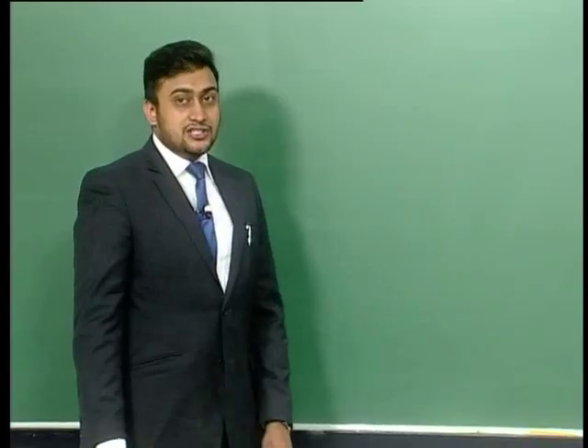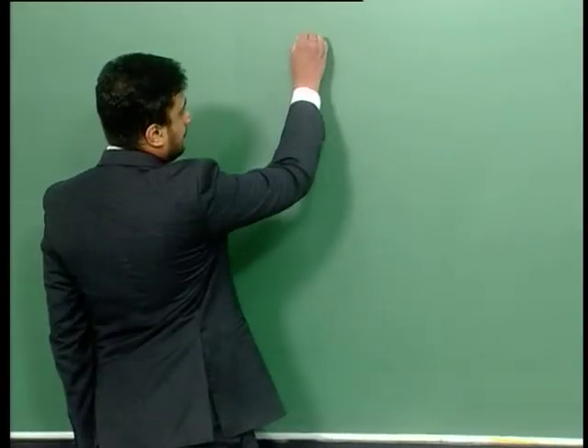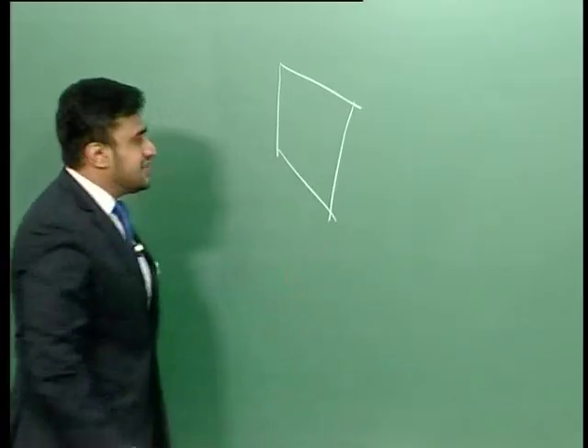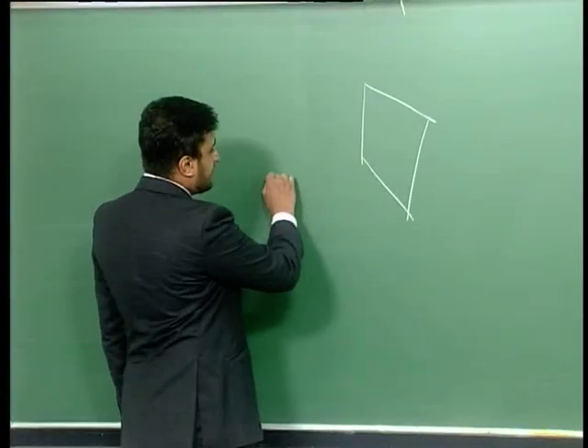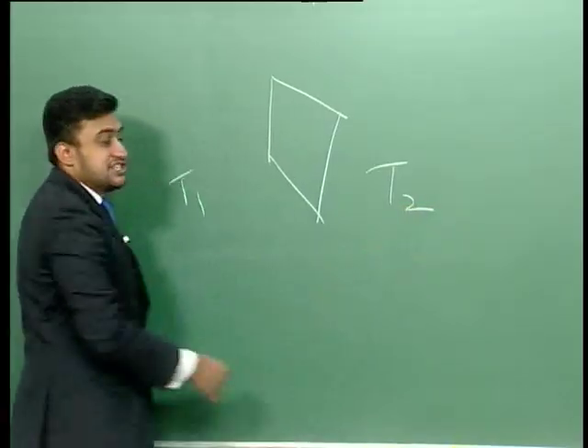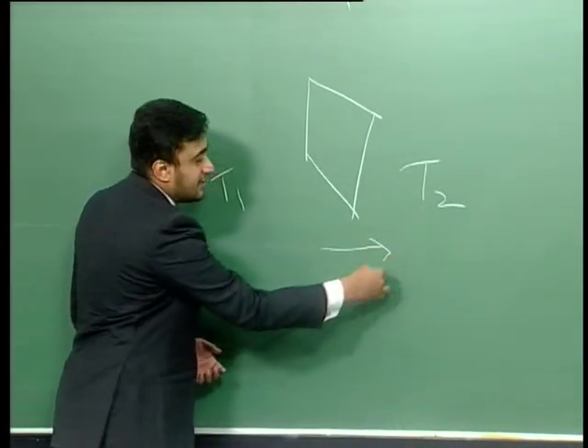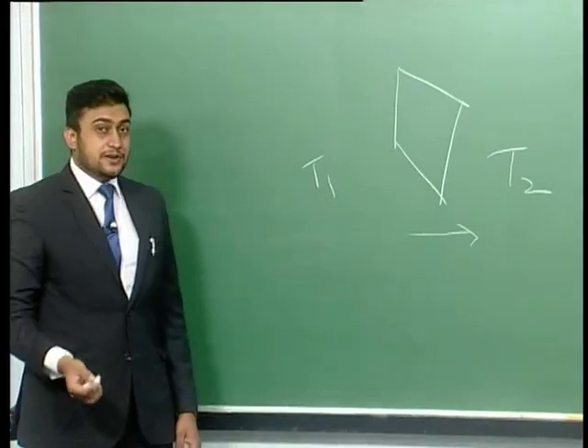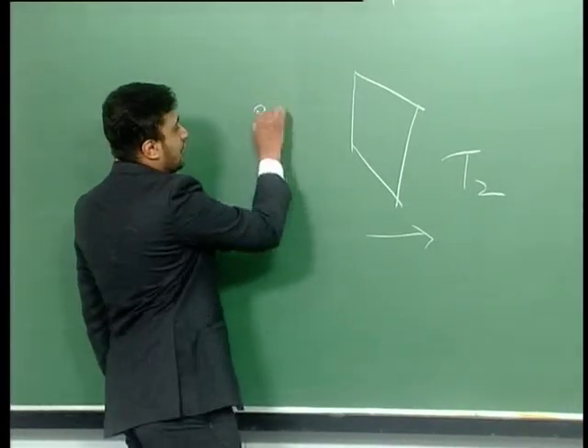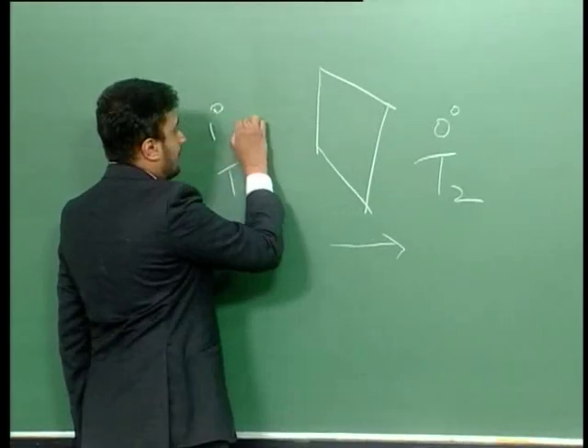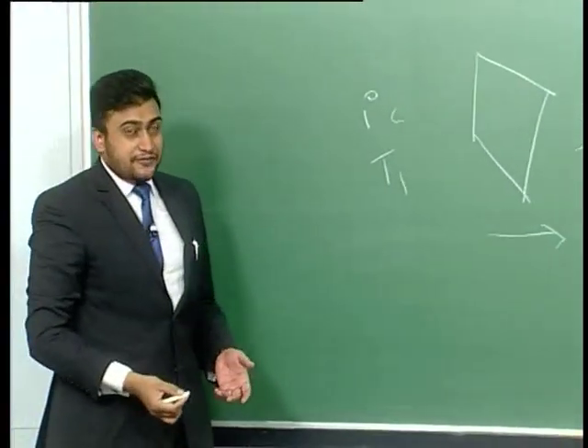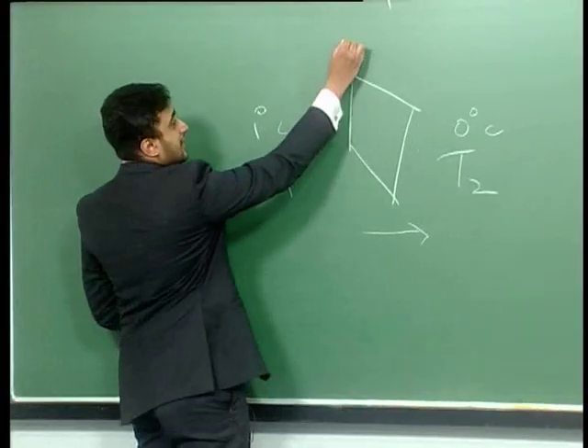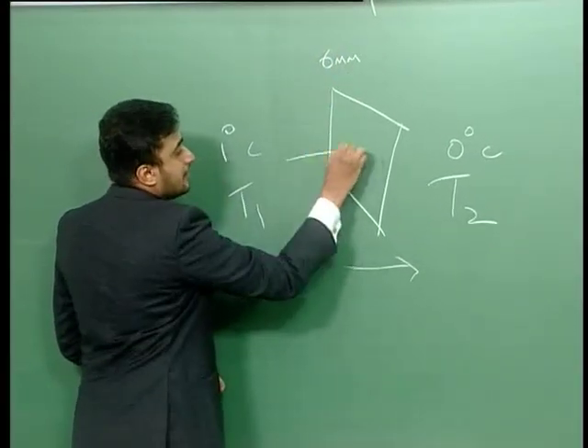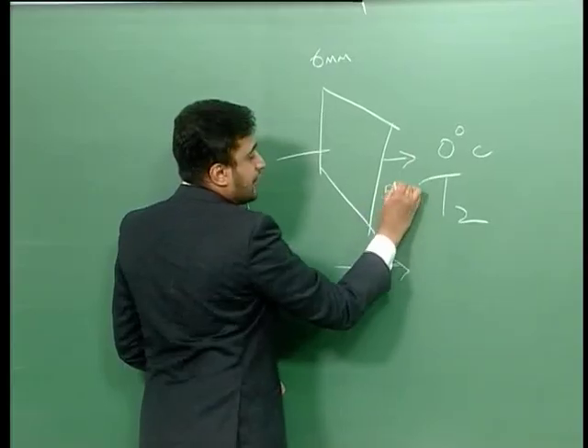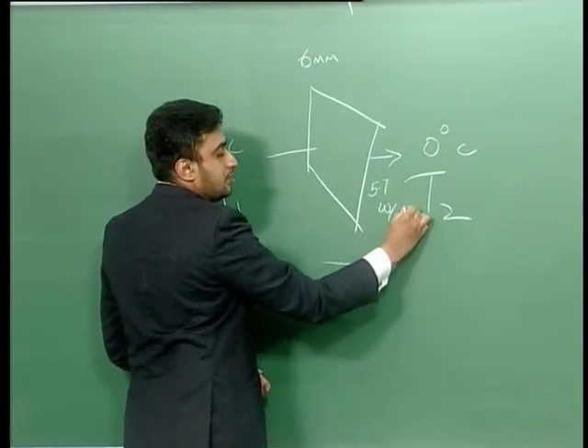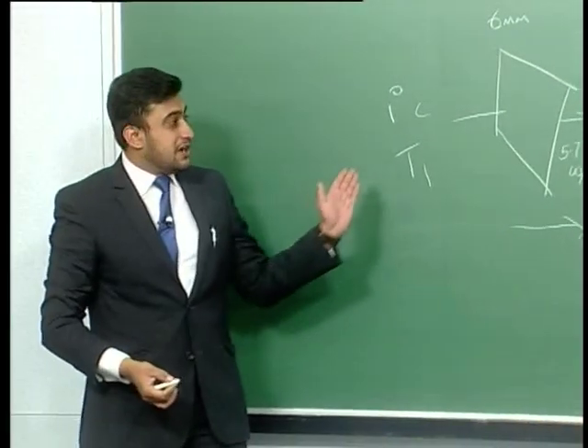The U value of glass, just to explain to you better on a board. If this is a panel of glass and you have two different temperatures on the exterior and the interior, what is the amount of heat transfer that occurs through the glass? It can be defined by your U value. So if you have a 1 degree difference in temperature for a 6 mm glass, about 5.7 watts pass through the glass.